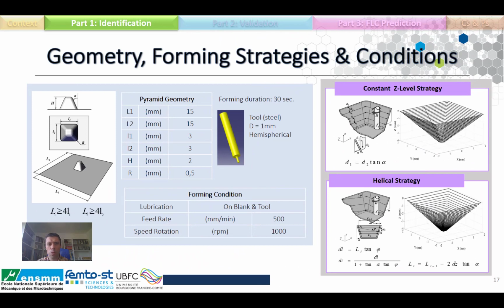So the geometry we use for the characterization test in this project is a tiny pyramid, as you can see here. The geometry we use corresponds to the width of the strip. So the pyramid has an area of 3 mm by 3 mm with 2 mm height. The forming tool has 1 mm diameter. The lubrication with oil is sprayed directly on the blank and on the tool during the forming.